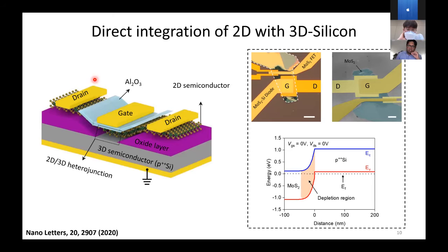Here is an example of how there is a 3D semiconductor wafer, which is silicon in this case. This is heavily P-doped. We open up a window in the oxide, and we stamp a 2D layer on top of it. Then we pattern electrodes over here. We coat ALD dielectric and put down the top gate. So basically, this is how the devices look. Here's an optical micrograph. Here's an SEM.